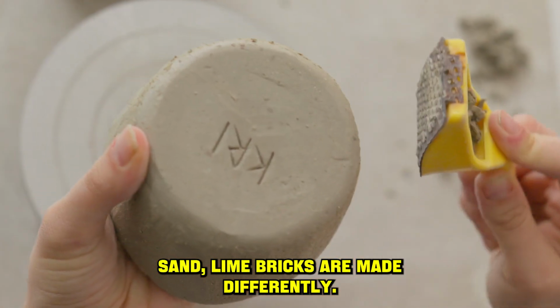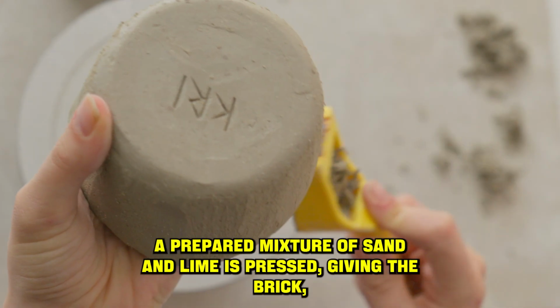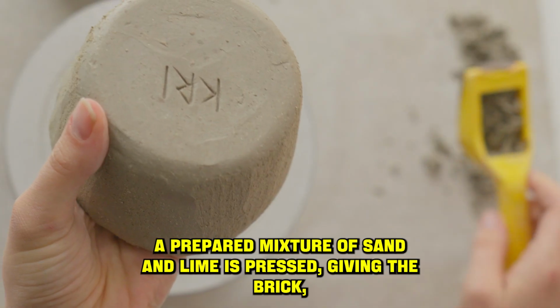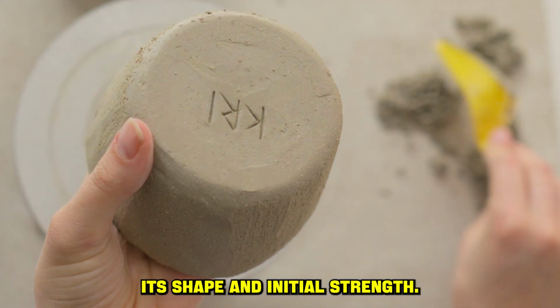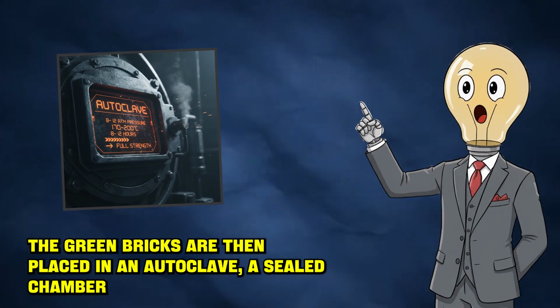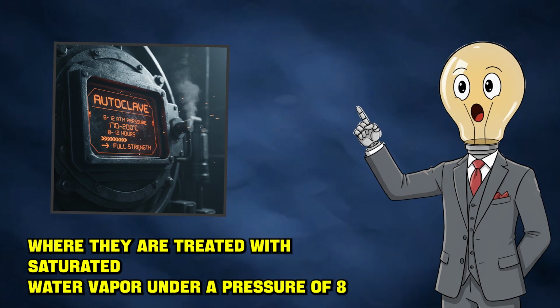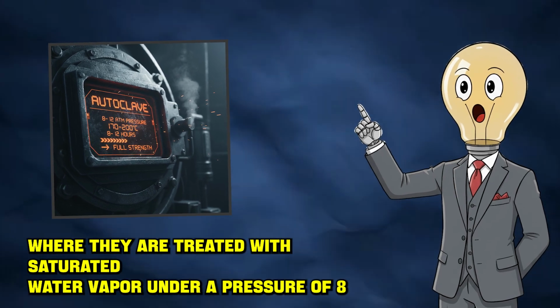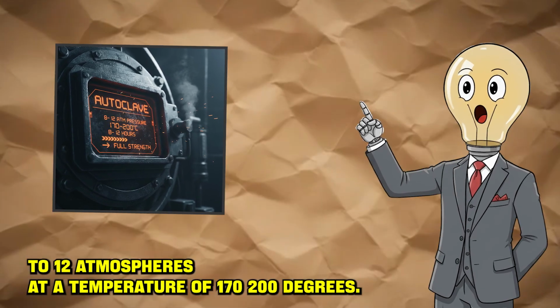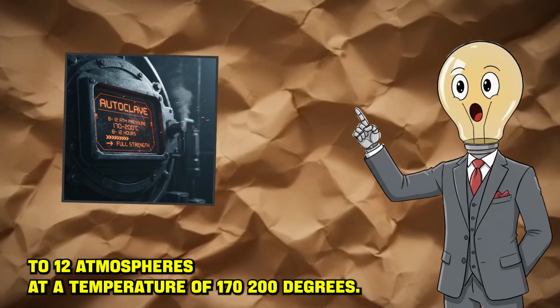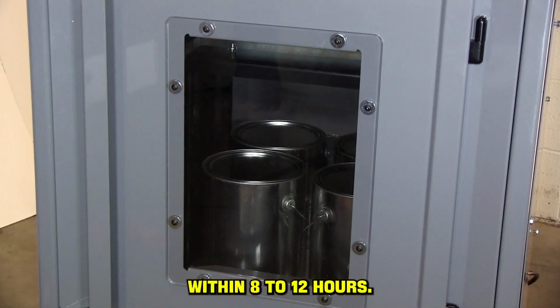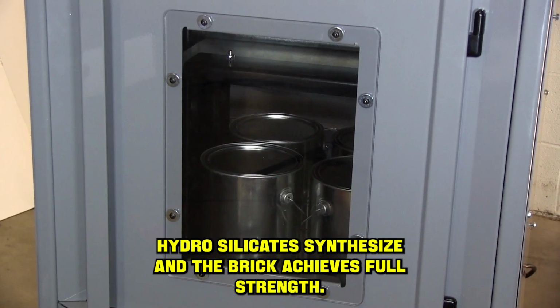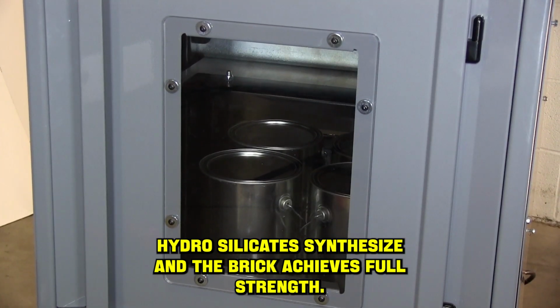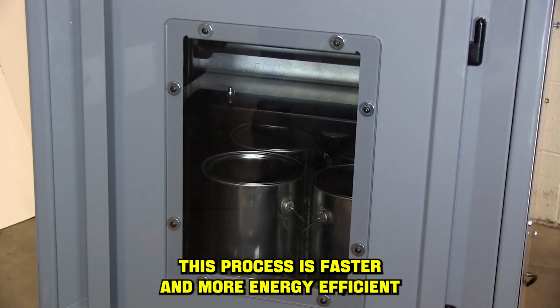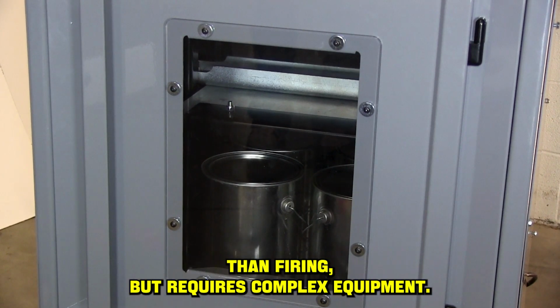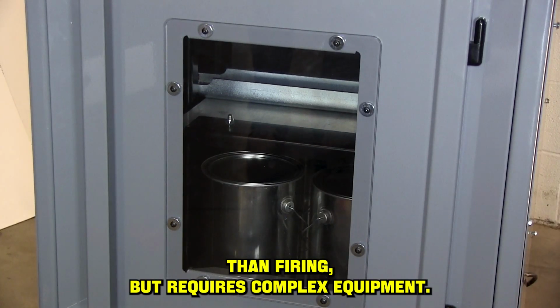Sand lime bricks are made differently. A prepared mixture of sand and lime is pressed, giving the brick its shape and initial strength. The green bricks are then placed in an autoclave, a sealed chamber where they are treated with saturated water vapor under a pressure of 8 to 12 atmospheres at a temperature of 170 to 200 degrees. Within 8 to 12 hours, hydrosilicates synthesize, and the brick achieves full strength. This process is faster and more energy efficient than firing, but requires complex equipment.